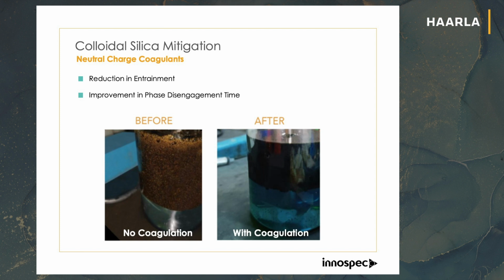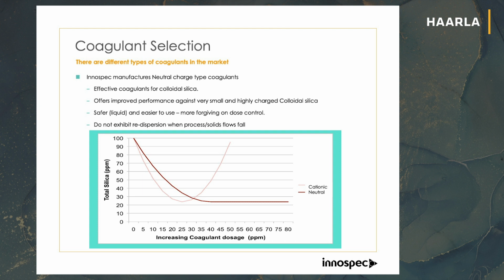What's the difference between the two different types of coagulant? Well, when you're looking at a non-ionic coagulant, you can see here the dosage response. You're looking at how effective it is in terms of increasing the dosage and removal of the silica. And then you're looking at the cationic one, where you increase the concentration, and you can see you get to a certain point, and then it's actually detrimental.